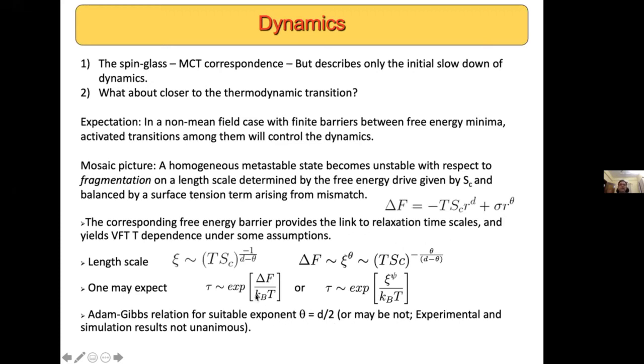So in particular, if one is looking at the first form, where the relaxation time is given by exponential of delta f star, a theta value of d over 2 would lead to the Adam-Gibbs form. There are other combinations if one plays with both the exponent psi and theta.